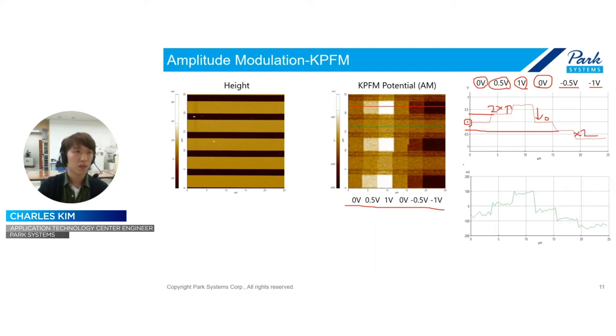But the disadvantage of the AM KPFM is the averaging effect. The AM KPFM is measuring the electrostatic force itself. You know, the force is quite a long range force. And because we are using a conductive material coated cantilever, the whole part of the cantilever works like an antenna detecting the electrostatic force. So even though this line is the grounded line, as the sample bias changes, the grounding line also changes its potential as well. So this is the disadvantage of the AM KPFM.